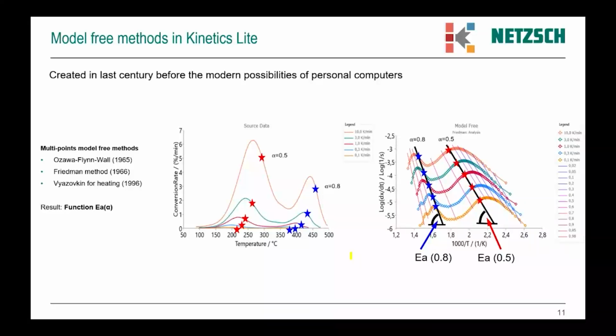The next type of methods in Kinetics Lite is multi-point model-free kinetics. Here, different points are taken into account. For example, for alpha 0.5, where we have only 50% of the total area, we have some points, we have a straight line, we have the slope, the activation energy for 50% of conversion. We can take points for 80% of conversion, where alpha is equal to 0.8, and we have new points, another straight line, and the activation energy at alpha equal to 0.8. We can make it for different values of alpha from 0 to 1, and the final result is a function where we have activation energy as a function of alpha. There are different methods, Ozawa-Flynn-Wall, Friedman, and Vyazovkin, and they are included in Kinetics Lite.